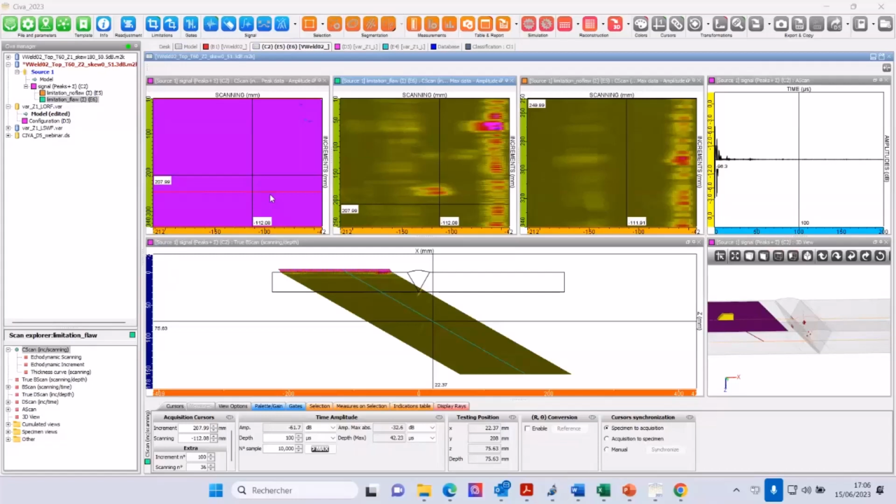This is what we did here. You run it in the simulation, and then you run it in the tank and you get that data. What we have found, trying to match it up with the spherically focused for what the best parameters are to run, is that we still sometimes are like 6 dB off from real life data. So what that's going to do is, if we use this, it'll help normalize to bring the real life data closer to the CIVA data, right?